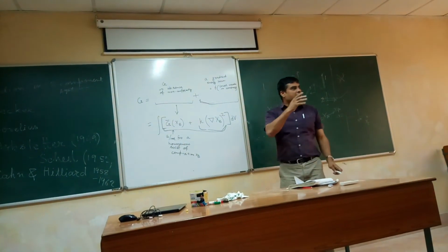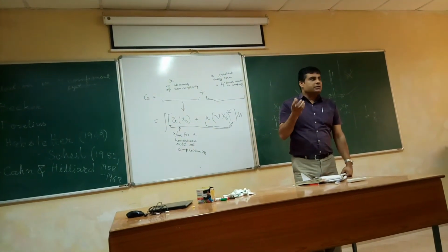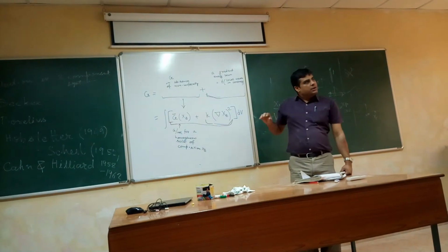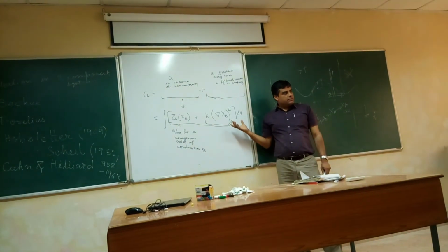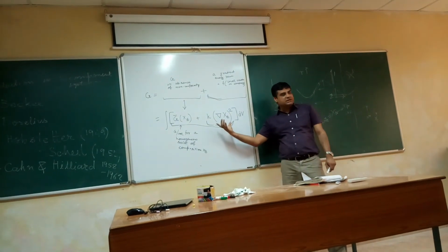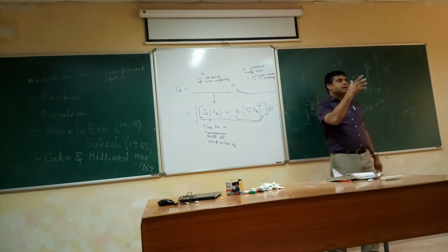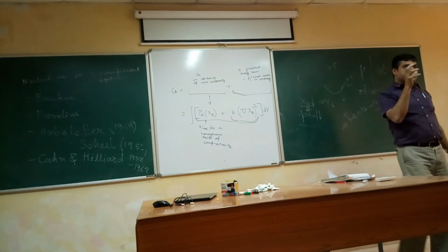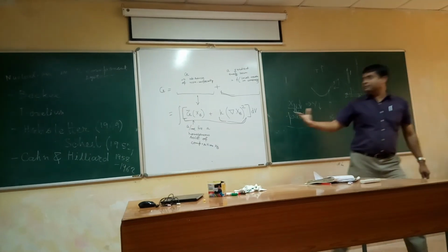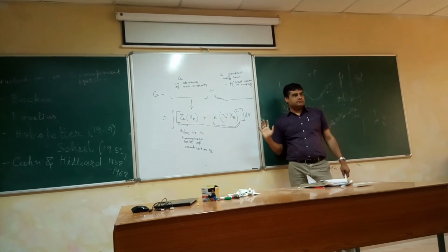If there is a local inhomogeneity, even though a new nuclei has not formed, new phase has not formed, just at the embryo stage, that local inhomogeneity also is taken care of by this term. And also, even if a new nuclei has formed, a new phase has formed, precipitate has formed, that interface is also taken care of by this term.